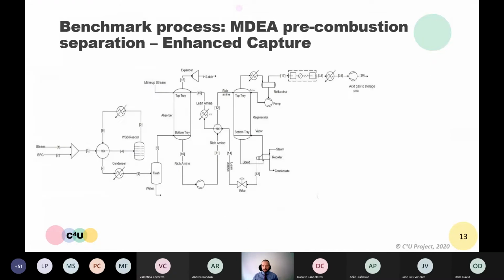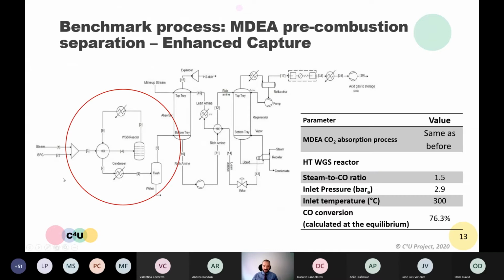There is also a second scheme, which is the one that we call enhanced capture. Now, compared to the previous one, the main difference here is that we also integrate a separation unit with a high temperature water gas shift reactor. This is operated at an inlet temperature of around 300, so water gas shift occurs between 300 and 400 degrees Celsius, while the CO2 capture unit still remains unchanged. What is happening in this case is that we can convert most of the CO into CO2 and hydrogen. This will be up to 76.3% according to the conditions selected in this process. And then we will have a hydrogen content which is about 24%. Nitrogen is 62%, and still some water is present in our decarbonized fuel.